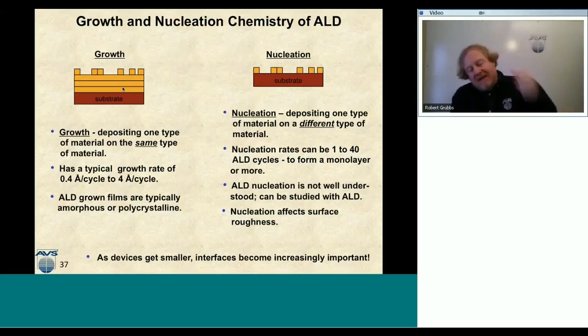So I might have to run my ALD chemistry 40 times before I actually get enough of that chemistry on all those surface sites to make a monolayer of my growing film, and then I'm off to the races. Then I'm in the growth regime where the ALD chemistry makes more sense. ALD nucleation isn't necessarily well understood, but it can be studied with ALD chemistry by doing a half cycle, analyzing the surface, doing the next half cycle, analyzing the surface, and watching the film evolve from your substrate to the deposited film. And I think that's a very interesting area of research.